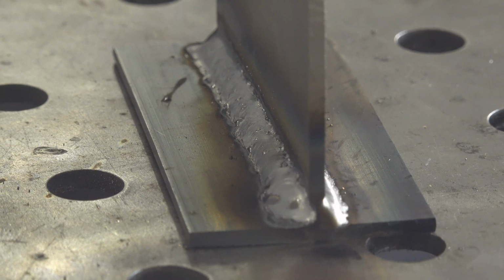Pulse mode on steel runs pretty smooth with 90/10 gas, maybe even smoother than the DP200. But it was more finicky about wire stick out. I could go from 90 amps to 230 amps, and the synergic settings were always usable, though I'd say at times the voltage seemed a bit high.